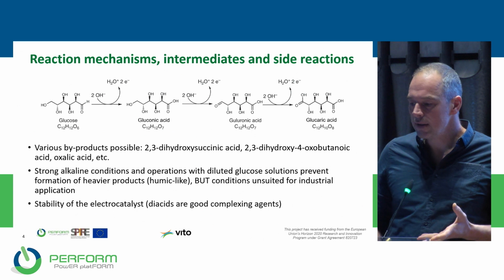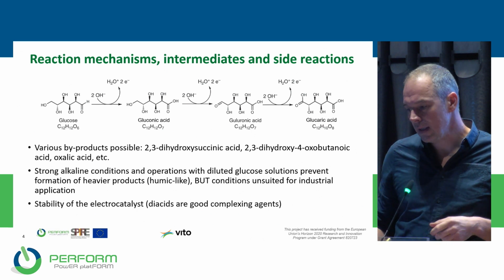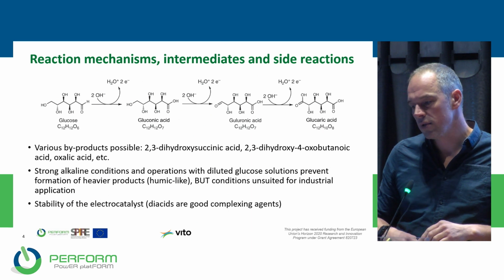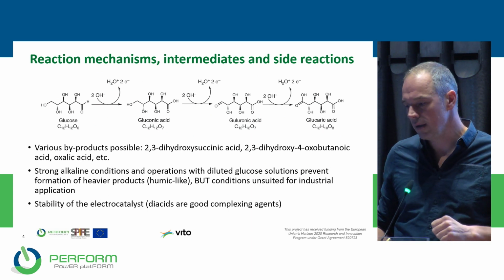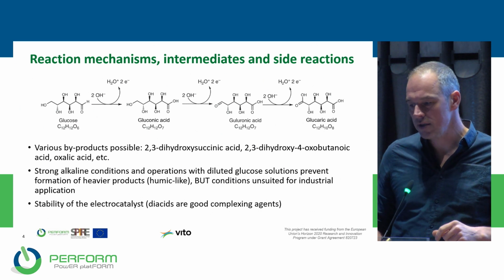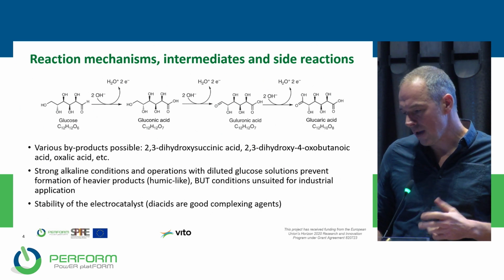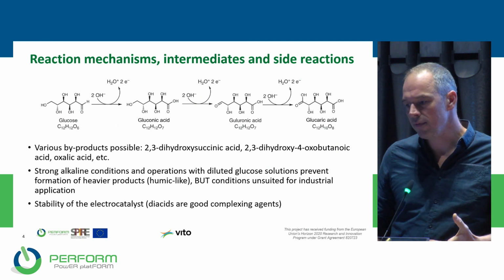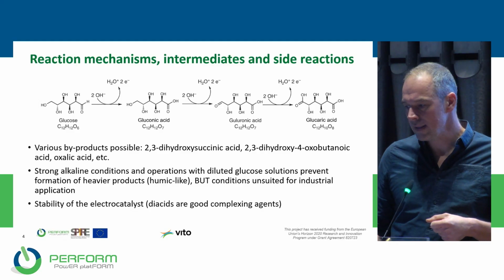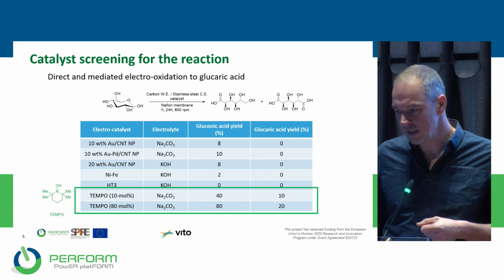There are some byproducts which are formed, like hydroxylated succinic acid, oxobutanoic acid, and oxalic acid. It requires strong alkaline conditions, and generally operations with diluted glucose will prevent humic-like products from being formed, but these conditions generally are not very suited for industrial applications. So for industrial applications, we want more concentrated feedstocks, basically. Of course, an important feature of the whole process should be the electrocatalyst stability. And as is known, diacids are very good complexing agents, so this could compromise this stability.